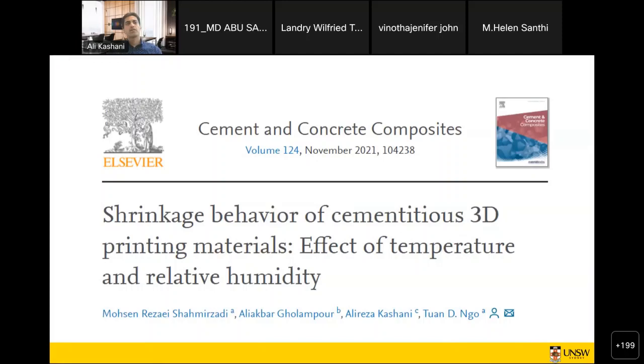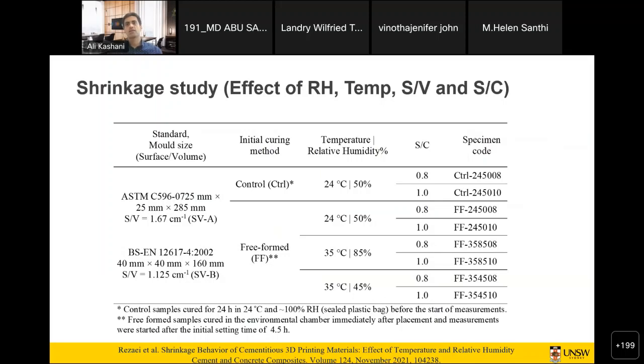So here are some of the projects and some of the work that has been published. This is work with my PhD students on shrinkage behavior of cementitious 3D printing material, the effect of temperature and relative humidity. In this project, we wanted to get a good understanding of the shrinkage that mimics the environment, especially for on-site printing, in conditions where you don't have any formwork. The standard shrinkage measurements, both ASTM and BS, the major standards that people refer to, keep the samples inside the molds for at least 24 hours. And for 3D printing, most of the shrinkage happens during those 24 hours. So it's not really representative of the shrinkage that is happening in this environment.